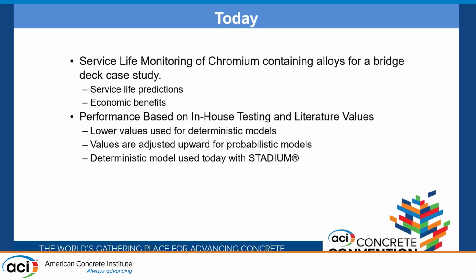A lot of the data, I'm not going to go into how all the data got there, but a lot of it's based on our in-house testing and literature values. For threshold values, we use slightly lower values for deterministic modeling, which I'm using here, but you can use probabilistic models. With probabilistic models, you can get the chloride threshold to be a little bit higher, because they'll cover the lower values due to the probabilistic distribution of the chloride threshold values. And then today I'm using Stadium.